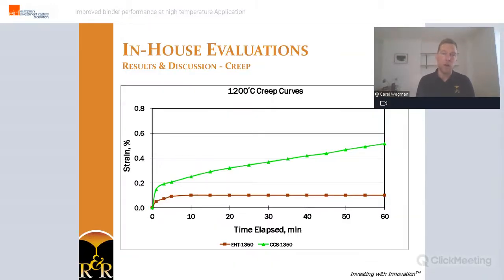But since this is R&D, we want to see where we would start seeing creep-related benefits of EHT binder. So by raising the initial firing temperature to 1350 degrees C and testing the creep properties at 1200 degrees C, we begin to see differences. The CCS, which is represented here in green, shows more deflection, while the EHT is more rigid, which is the brown line. So this indicates that as the firing temperature increases, the binder begins to perform differently from a creep standpoint. And this trend is in agreement with the conventional knowledge that firing the shells to a higher temperature can be a solution to resolve bulging issues.